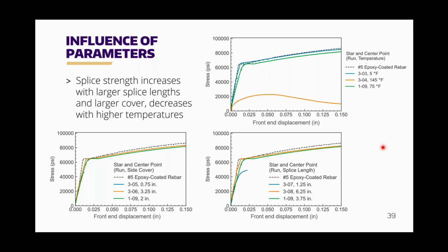For reference, we've shown in the dashed black line the response of a number 5 epoxy-coated rebar. How we calculated that value is we took the stress-strain curve that we measured as part of the test series and multiplied it by the free length between the top of the specimen of the HCSC and the location where we measured the front end displacement. If you see a difference between one of these curves and the black dashed line, you would interpret that to be slip. You can see that for the most part, you're seeing very little slip for many of these curves. You can also start to see the slight differences in behavior at the extreme ends of our design space.